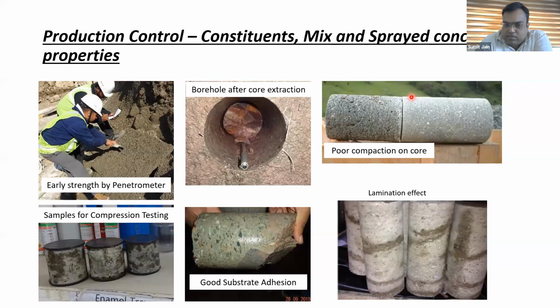And on the right top corner, you can see comparison of 2 cores. One core is having a very poor compaction. This usually occurs when the compaction pressures of the machine are very low, and this is not going to give you any strength at all. And this is a good compacted core, where there is no imperfection and everything is smooth. At the bottom right corner, you can see samples which are having a lamination effect. We're going to discuss in the next slide why this happens.